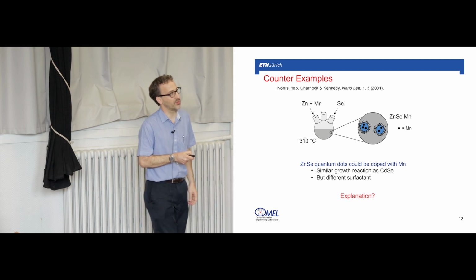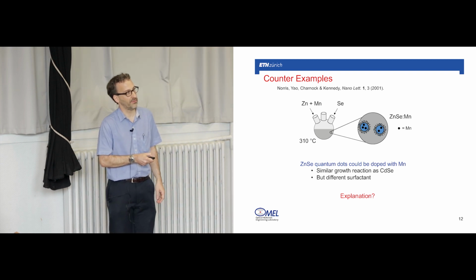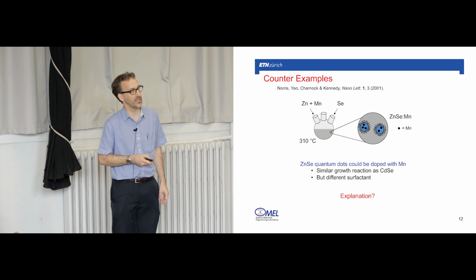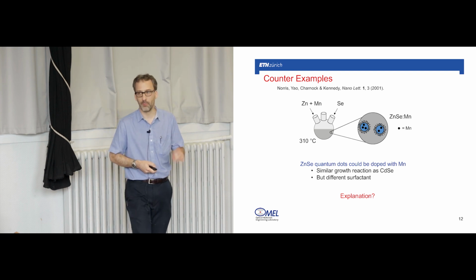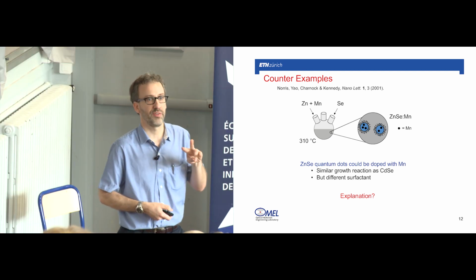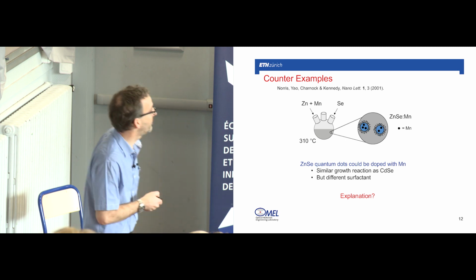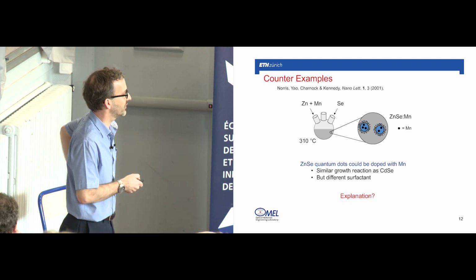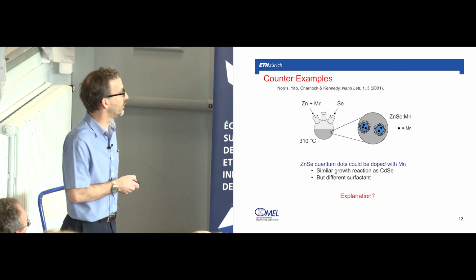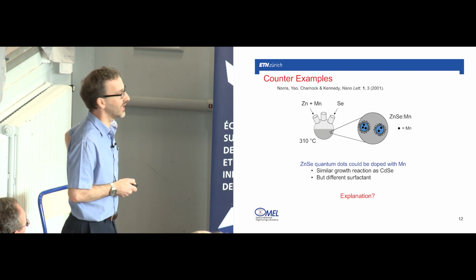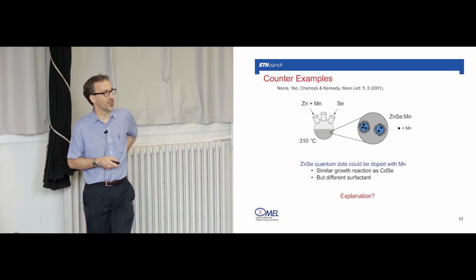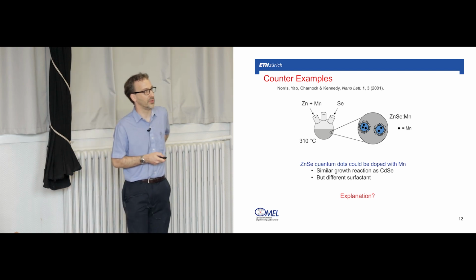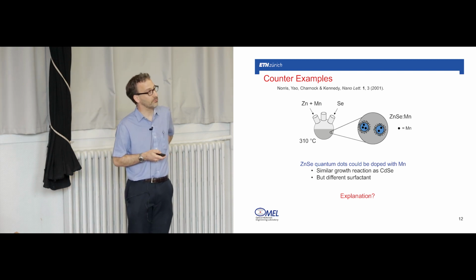And so this was kind of confusing because these were very similar growth reactions, zinc selenide and cadmium selenide, but by luck, they used different surfactants. So TOPO, trioctylphosphine oxide, was used for cadmium selenide. It turns out to be bad for doping. And in this prep, you use hexadecylamine. And it turns out that that affects the kinetics of the doping, as I'll mention.